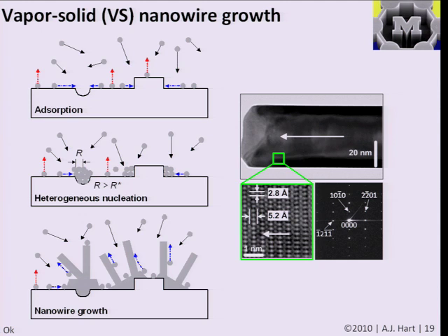And it turns out that after you go from this nanoparticle regime to, say, the nanowire regime, the same things happen, but atoms actually can hit the substrate and can diffuse all the way along the wire and incorporate at the tips, or they can go directly from the gas phase to the tip of the wire. And so that's one example, which is kind of a crossover regime between growth of a film and growth of nanoparticles and growth of nanowires, all following this basic process from which you start with a gas phase precursor and you control the conditions so you nucleate and you grow the material. And you understand how the materials stick and transport and unstick.